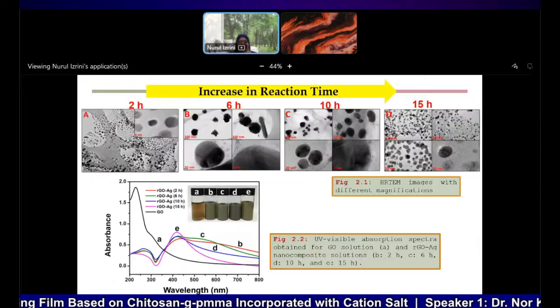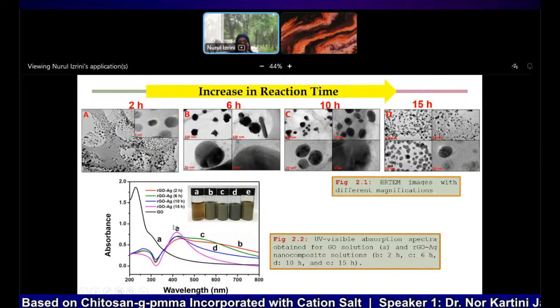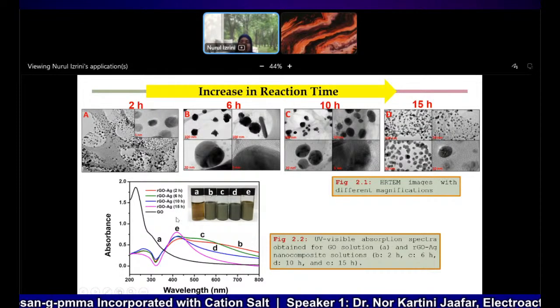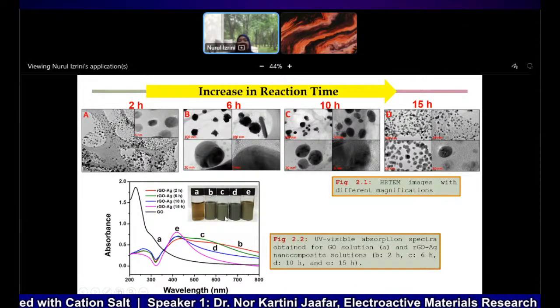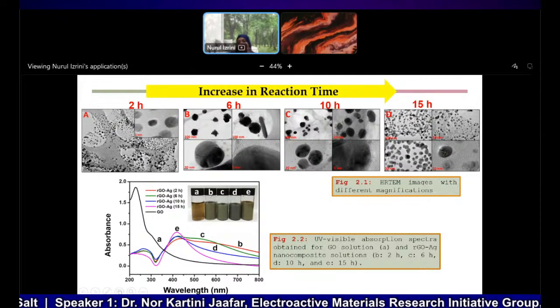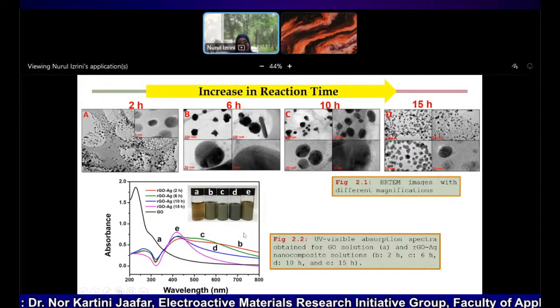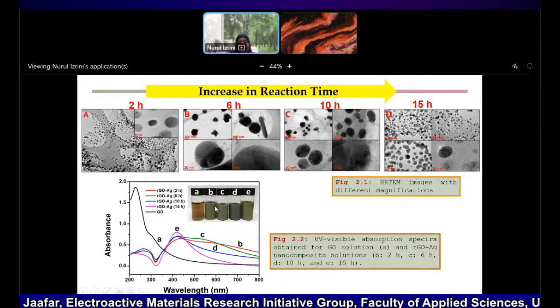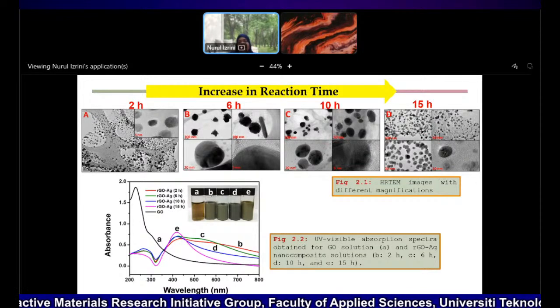So of course we ran the UV-Vis first to confirm the formation, and we can see the difference in color at every reaction time, every synthesis time. This is before the reaction, and this is after the reaction at different hours. We can see that the visible color changes in the nanocomposite at different reaction times, which indicates changes in the aggregation state, size, and shape of the silver nanoparticles.